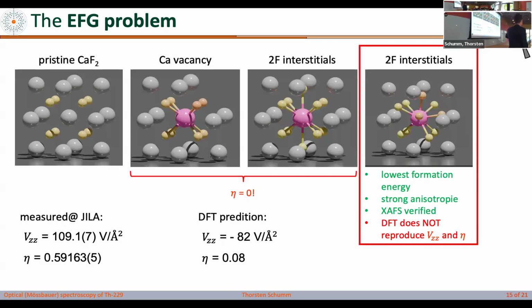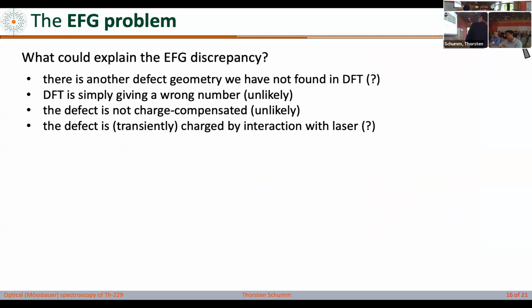Then you could say, oh, maybe it's the other ones. Maybe we got that wrong. Maybe it's still this one here, right? The lobes are here. This one is somehow similar from a chemist's perspective, but the arrangement is slightly different. The problem with these two is they actually have no anisotropy parameter at all because they are strongly symmetric. So they don't qualify either. So there's something that seems to make a lot of sense, but it doesn't fit the experimental data, and that's worrying us a lot. We're kind of scratching our heads.